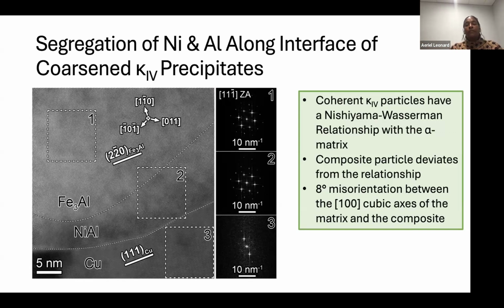But it was an important finding because, A, it wasn't Kappa 5, which people had said it was. And it wasn't Kappa 2 either. Kappa 2 is another iron-based phase that people, because of the globular shape, will sometimes just say, oh, it's globular, so it must be Kappa 2. What this showed us was that all of these things in the literature that had been reported as Kappa 5 and Kappa 2 are probably just this kind of shell-like composite structure.